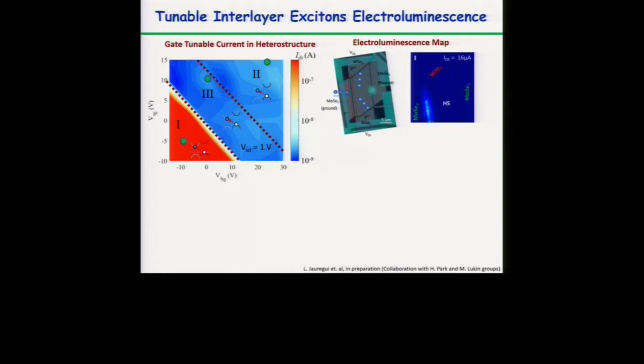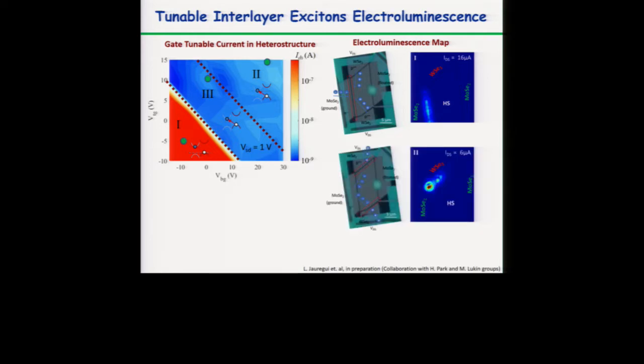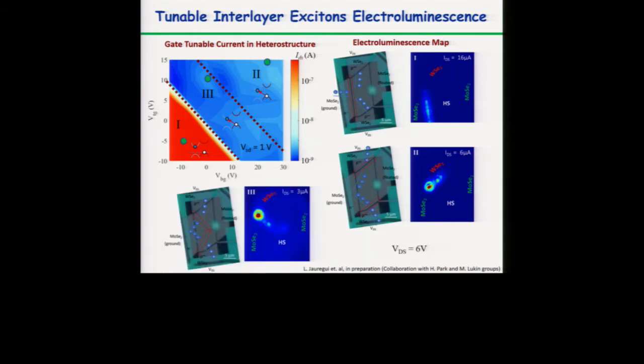Depending on where we place the gates, the top and bottom gate, we can get light out on this edge, the side edge, the left edge, or the top edge. Most of the recombination happens in this corner, but we can also get recombination in the center, depending on how we dope the heterostructure. It goes from 1, 2, and 3. This is also the configuration for the gates. We're either doping mostly tungsten diselenide, doping mostly MoSe2, or we are in an intrinsic region, and so we can control where the recombination comes from spatially.